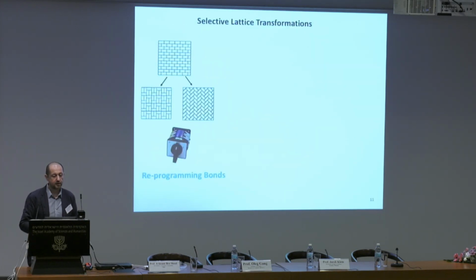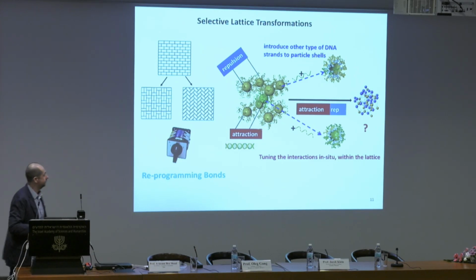It's much more exciting to think about how we can reprogram bonds on the fly and change the global state of the crystal, for example, to go from one symmetry to a completely different type of symmetry. And again, it's not induced by any conventional physical parameters, but rather by specific DNA strands. The way it can work: if we create a system which is the same type of BCC lattice I told you about before, this crystal is essentially balanced between repulsion and attraction. However, after the system is already formed and the crystal is stabilized, if I can change the shell on the fly, the system needs to find a new equilibrium state. As a result, this balance between attraction and repulsion is shifted, and a new type of crystalline organization can occur.